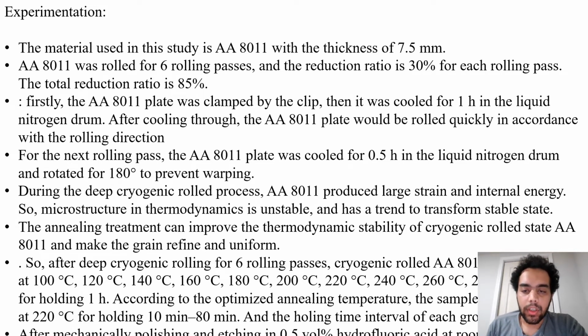So the experimentation is done in 6 phases. Obviously, we're using the AA 8011 aluminum specimen here. It will be rolled in 6 phases, and the reduction ratio is 30% for each rolling pass, and the total reduction ratio is 85%. Firstly, the aluminum plate is clamped by the clip, as shown here in the first figure. It is cooled for 1 hour in the liquid nitrogen drum. After cooling, the aluminum plate will be rolled quickly in the rolling direction. For the next rolling pass, the aluminum plate will be cooled for half an hour in the liquid nitrogen drum and rotated 180 degrees to prevent warping.